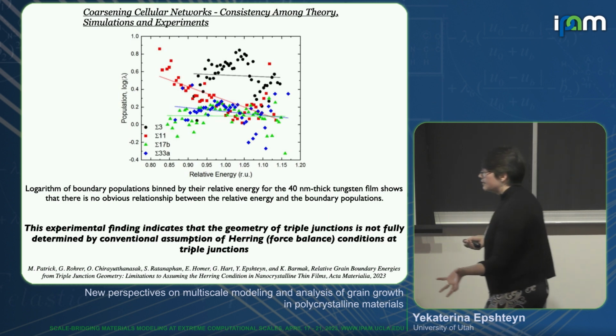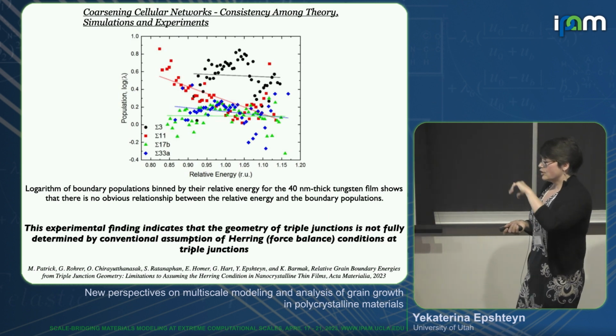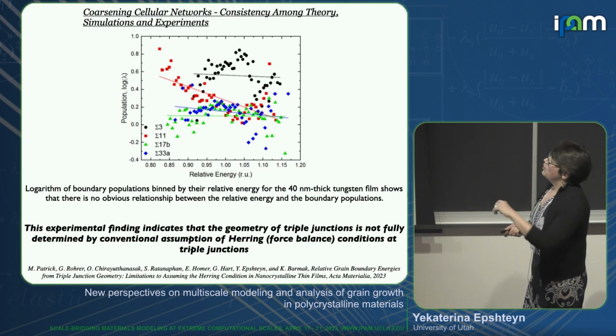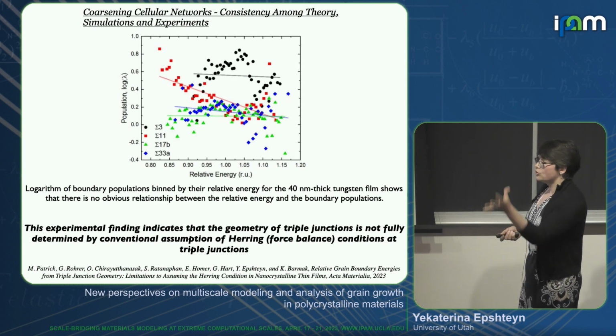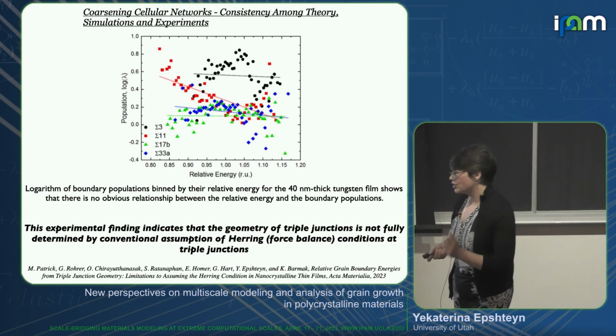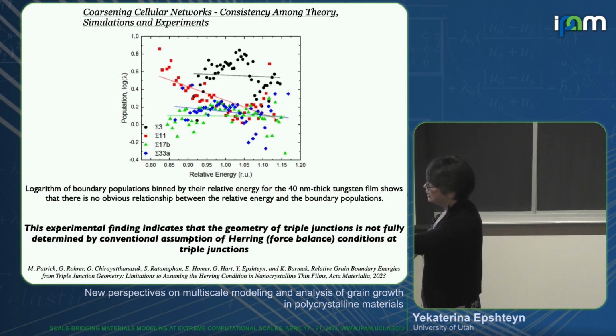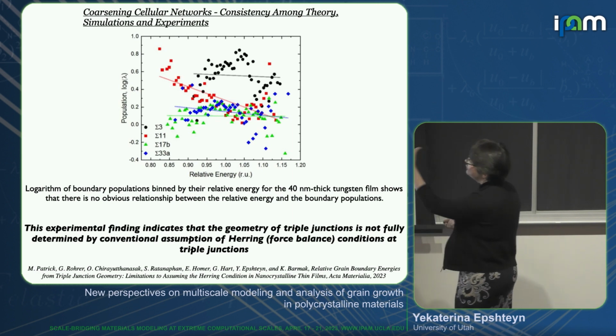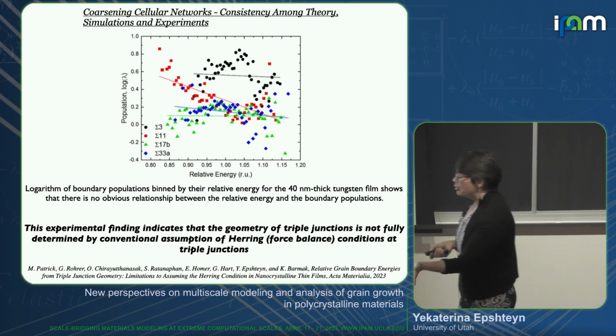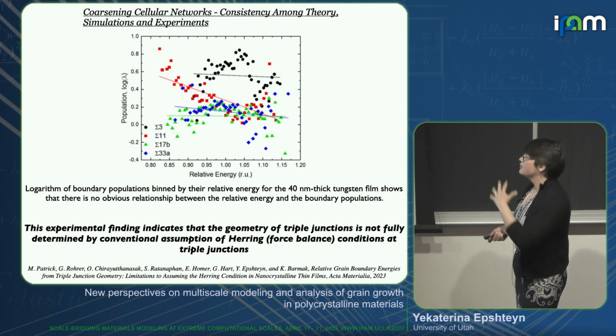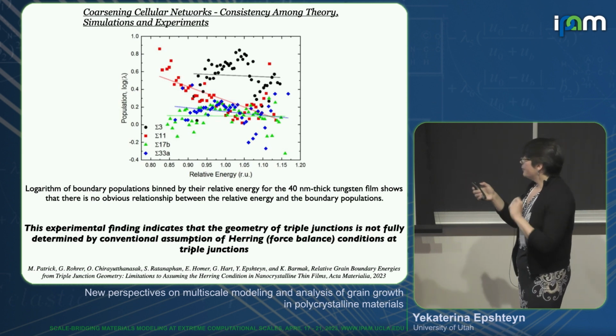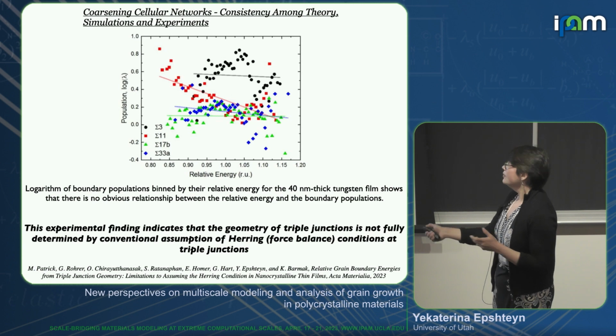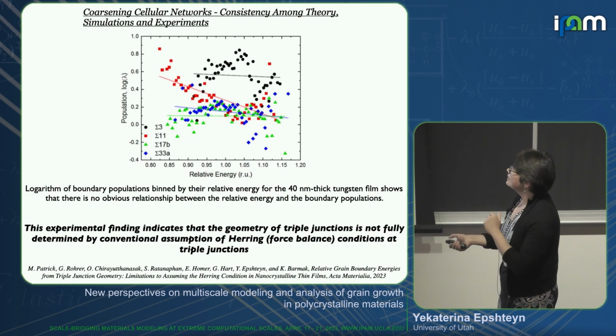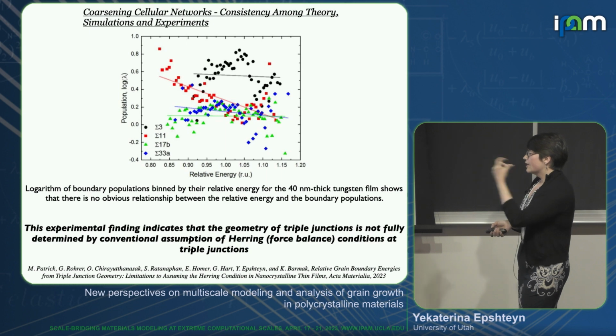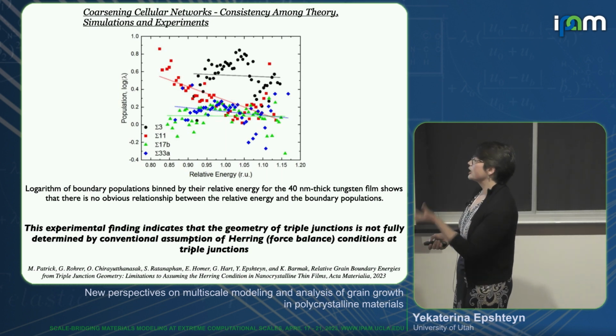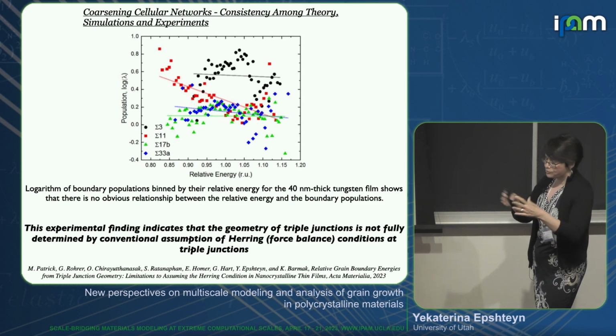So you do expect that in your system you will have a much larger percentage of low grain boundary energy, much larger percent of grain boundaries with low energy, much smaller percentage of grain boundaries with higher energy, and using these thin films, when we try to extract the data and process the data under assumption of force balance